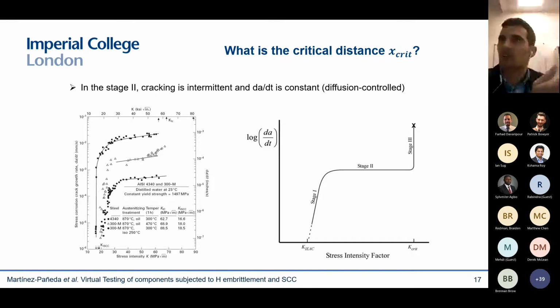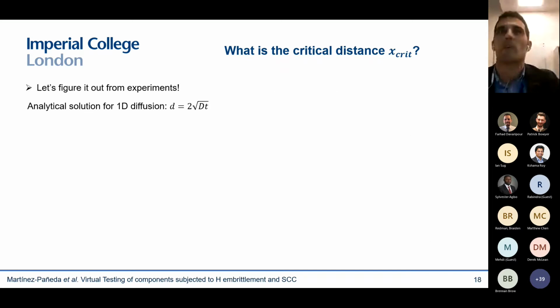This means that since we know how long it takes for the hydrogen atoms to travel a certain distance, we will be able, by measuring the crack speed in an experiment, to indirectly determine how long those atoms need to travel. What is this critical distance ahead of the crack? And as I said, you can take, for example, this 1D diffusion equation. So this tells me the distance that those hydrogen atoms travel is equal to 2 times the square root of the diffusion coefficient of the material and the time.